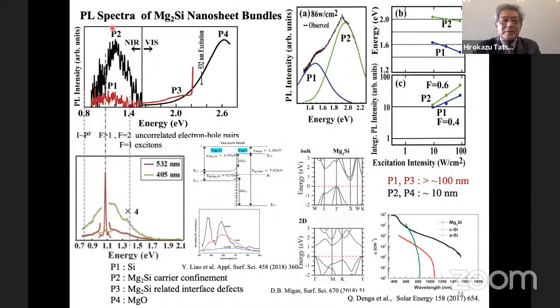This is a photoluminescence spectrum of the magnesium silicide nanosheet bundles. This is a luminescence from the silicon substrate, and some peaks are still observed even in these samples. These peaks are already known to come from surface oxide layers or remaining MgO. But a new peak appears for these materials. We discussed that this peak also originates from such nanostructures. So future investigation will be required to prove these discussions.